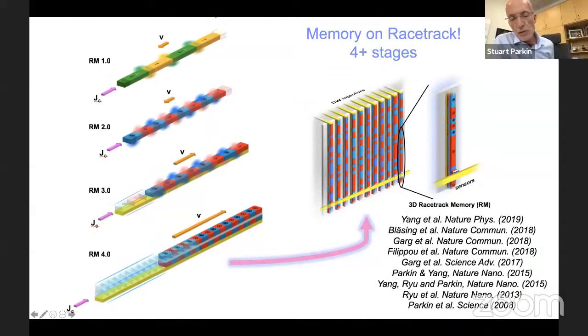And similarly, in Racetrack Memory 4.0, which makes the technology useful, we could create a racetrack in which the dipole fields from the individual domain walls are eliminated by building something called a synthetic antiferromagnetic racetrack. And this is actually something I invented in the early days of the spin valve technology. And it was even used in IBM's very first spin valve in 1997, because it creates extremely stable structures and it eliminates long-range dipole fields, which otherwise cause interaction between magnetic layers, especially on a nanoscale, where these dipole fields increase inversely with the size of the device.